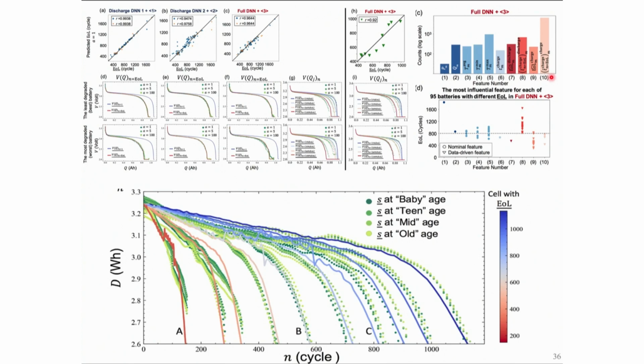For example, there were previously propositions where you can look at the change in the capacity from cycle to the next cycle, the temperature rise, or the change in impedance. So by comparing to those features, we show that the computer is actually able to resolve very subtle features, because on each charging and discharging curve, there are 500 data points that humans cannot detect, but the deep neural network is able to predict.